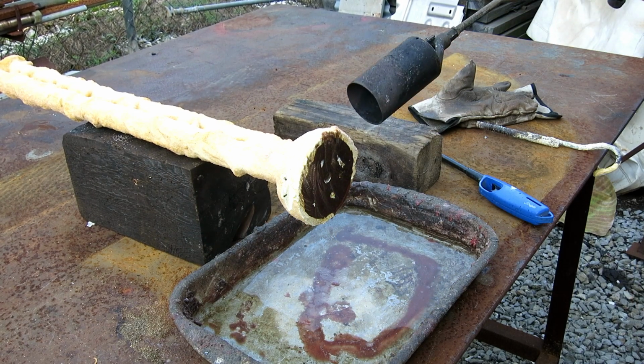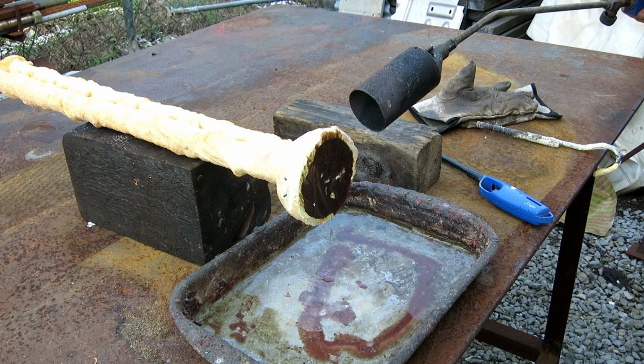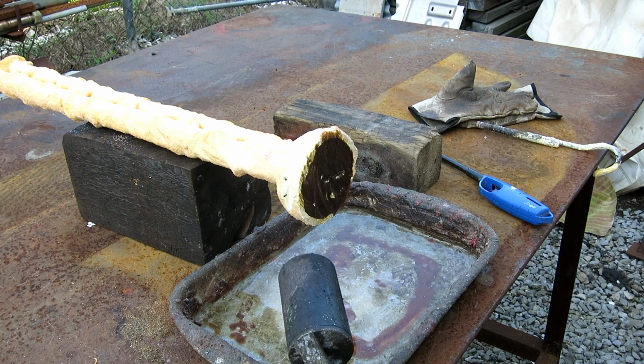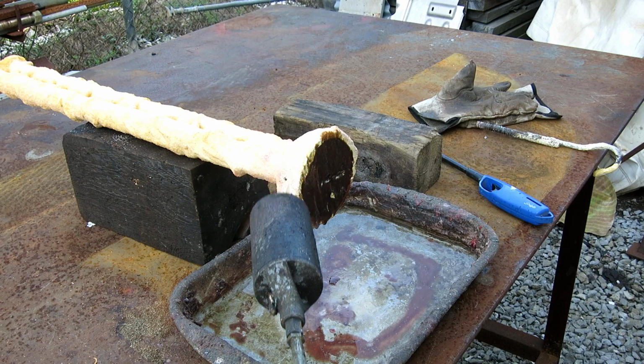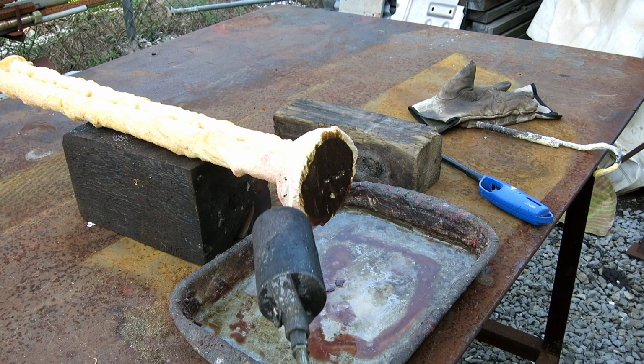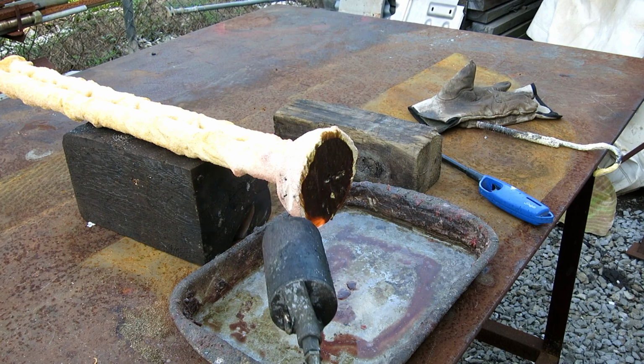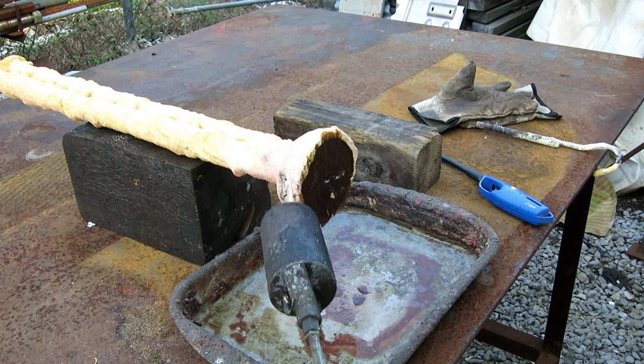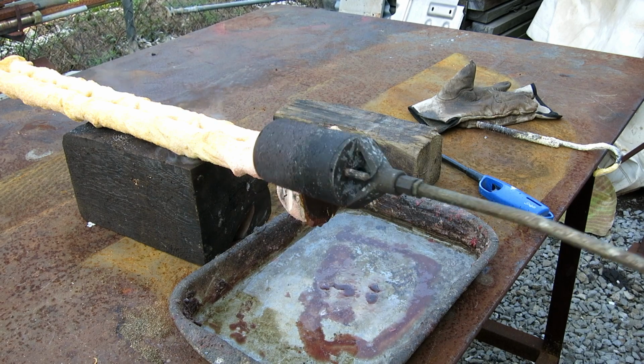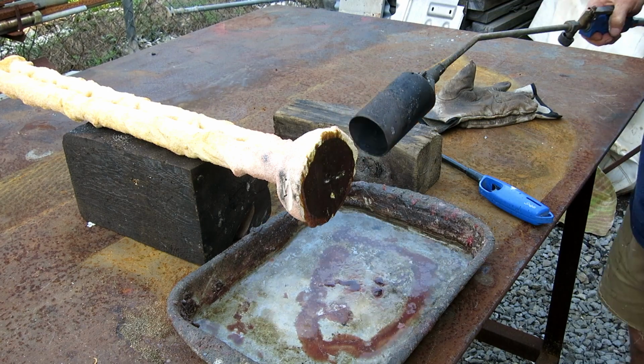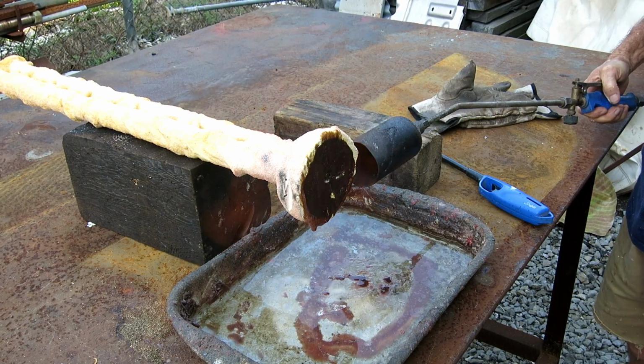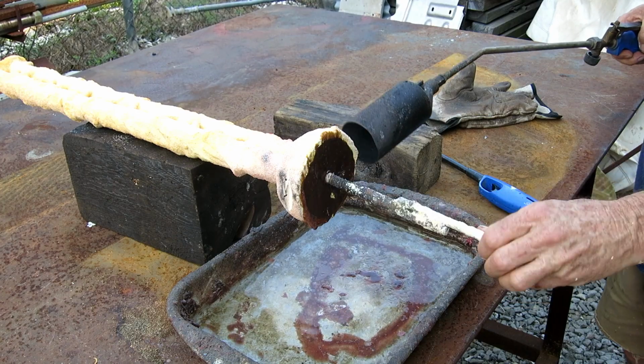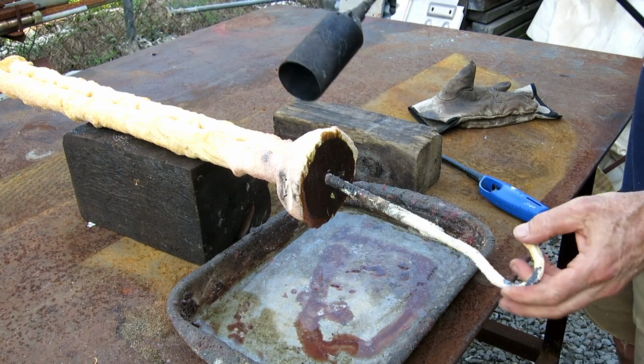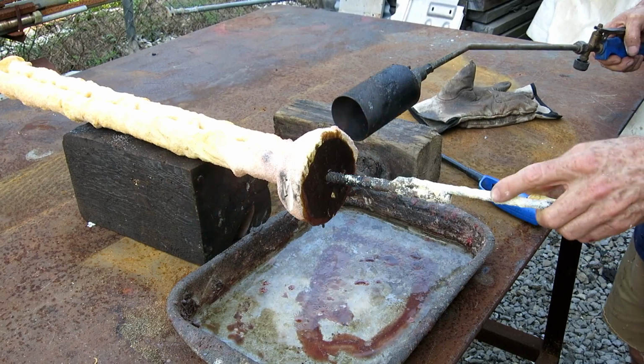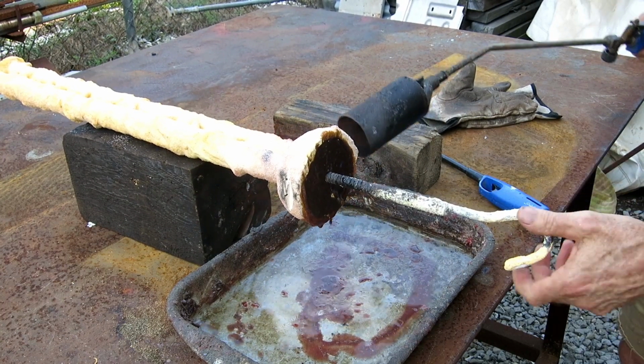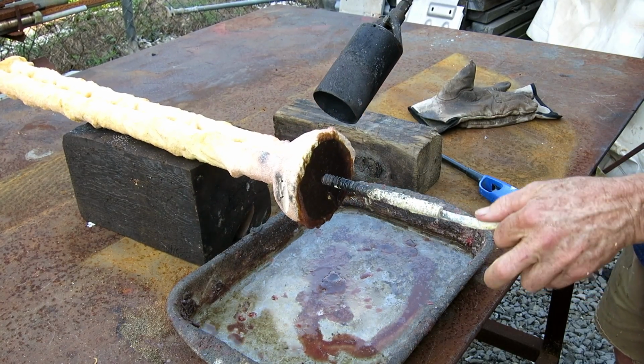I always burn out these wax cups before I put the mold in the kiln. There's a metal plate in this wax cup, and it's a big mass of wax, and it'd probably be the last thing to start melting in the kiln, and it really needs to be the first thing, because the wax in the mold is going to expand when it gets warm, and it needs a place to go or it'll crack the mold. So if you leave this big hunk in there, you're more than likely going to get a bunch of cracks in your mold. And if you remove it, it makes it real easy for the wax to start pouring out the bottom.